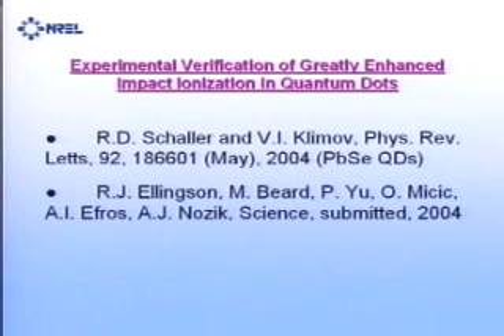And we were looking for this for many years. We started about 1981 or so. But we were looking at materials where this process was difficult to see, and we were scooped in May by Victor Klimov at Los Alamos, who found this to be very efficient in lead selenide. We were looking at the III-Vs, indium arsenide, indium phosphide, and other III-V low band gap semiconductors. So we jumped to lead selenide after. I actually got this to review in February, so I got a couple months jump on this. So we jumped into lead selenide, and we found some very interesting properties which went beyond what was published by Klimov, in particular the model for this.